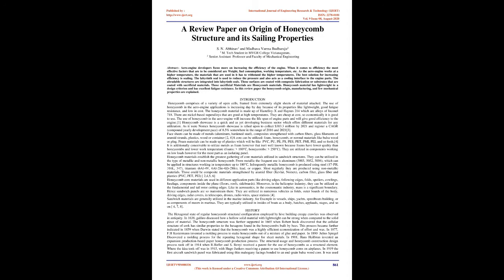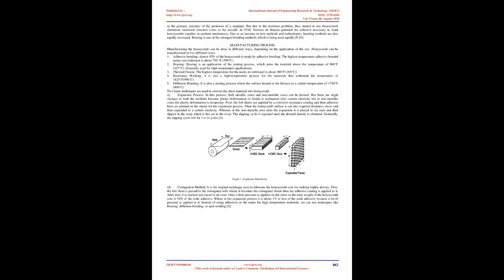Honeycomb materials constitute the largest group of core materials used in sandwich structures. They can be used in the form of metallic and non-metallic honeycomb. From metallic, the frequent use is aluminum, 3003, 5052, 5056, which can be applied in structures working in temperatures up to 180 degrees Celsius. Infrequently, metallic honeycomb is produced using steel, 17-4 PH, 316L, 347, titanium, 6Al-4V, 6Al-2Sn-4Zr-2Mo, lead, or copper. Most commonly they are produced using non-metallic materials.